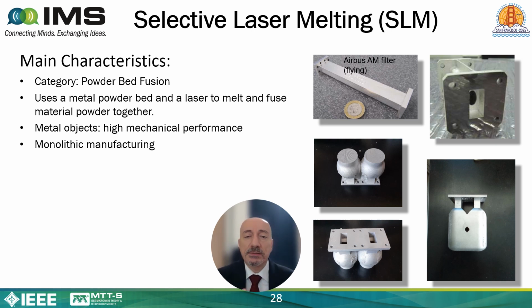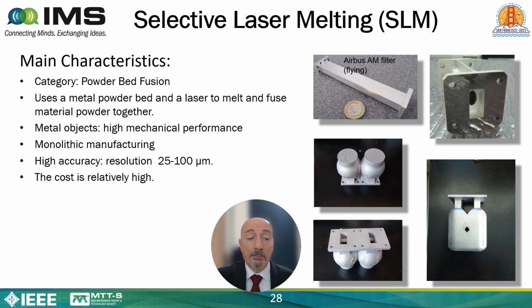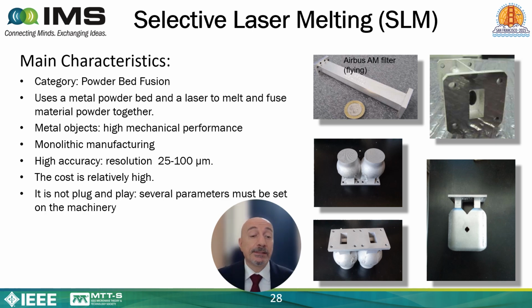screws, and this increases the weight of this object. And then when you attach two metallic parts, you also risk that ohmic losses increase the losses of the components. So this is really an advantage, the monolithic manufacturing. The accuracy of this technology is quite high, by the way, because the resolution ranges from 25 to 100 micrometers. Unfortunately, the cost is relatively high. And it is not plug and play, so you need an expert operator.